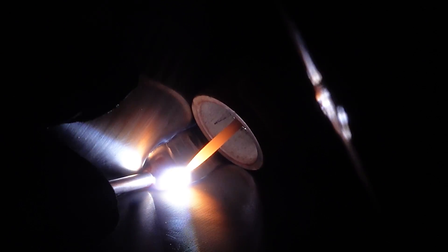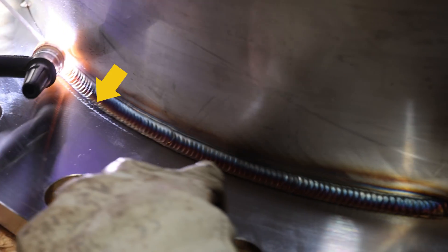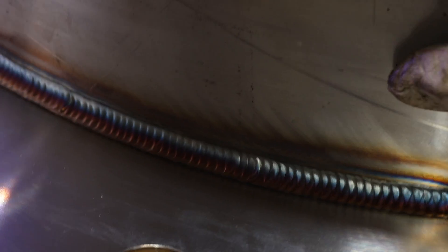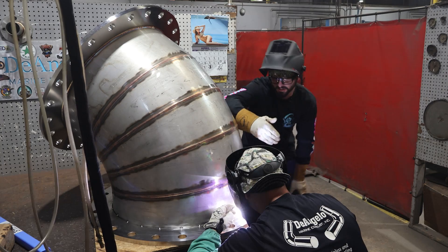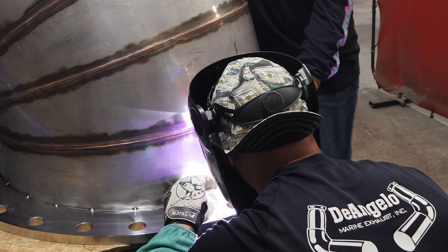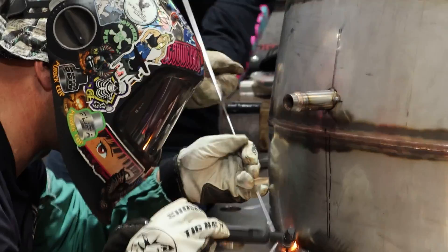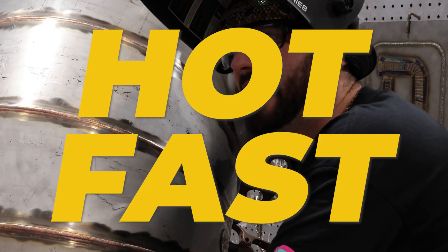Stan, I think this robot's going to eat your lunch. Not by looks it won't. He's really bouncing off that top, getting up there and then coming right back down to not put too much heat on that 12 gauge — because we cannot burn through, so we've got to be very careful. So you can see from walking the cup, some companies won't allow this because you've got a little scratch mark along the stainless. But you can see this is two different thicknesses of material. The oxides are a little more heat affected right there across the top because of the thinner 12 gauge steel. We're at 3 minutes 45 seconds, we've got at least a foot and a half. Hot, fast, blast the gas.